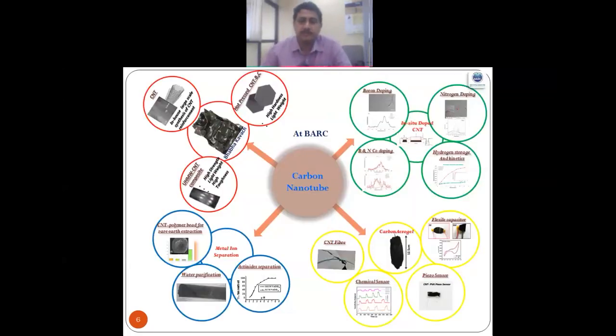At BARC, we are using carbon nanotubes for some special applications. Here in this slide, you can see them. At the leftmost top side, you can see that we are using carbon nanotube powder along with ceramic matrix to produce boron carbide carbon nanotube composite by hot pressing. Also, they are used with ultra high molecular weight polyethylene. So it is polymer carbon nanotube composite. And these two have been used in Bhabha Kavach, which is a lightweight ballistic resistant jacket.